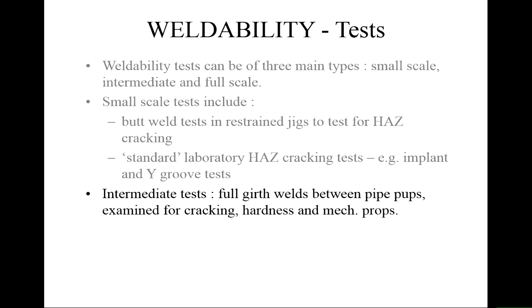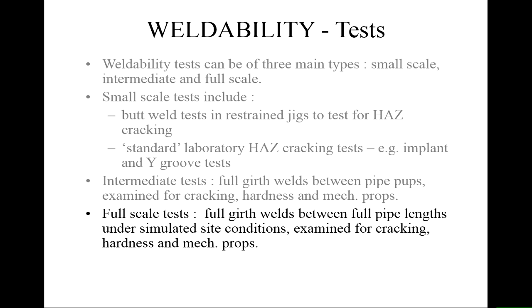Intermediate tests you have to do, that's full girth welds between pipe pups. A pipe pup is a short section of pipe. And this is often what you do for welder training. And then you can cut that pipe section up and you can do hardness tests, cracking tests, mechanical tests, and get some indication of how it varies from welder to welder or from position to position. And you need to do those tests. And then you finish off with full scale tests, full girth welds between full pipe lengths, simulated site conditions, everything that you wanted.